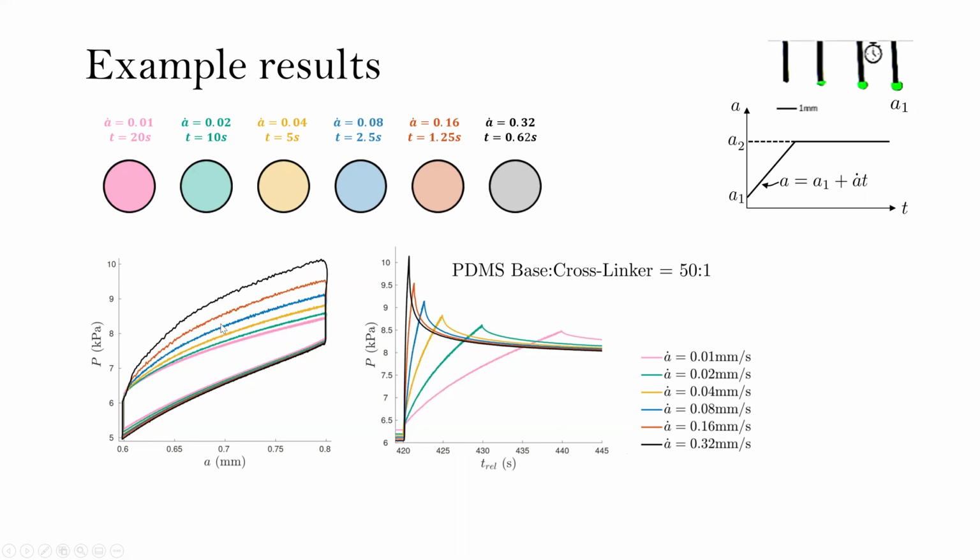We can also see a clear rate dependent effect, where the pressure clearly stiffens based on the stretch rate that we are working with. There's also significant viscoelastic relaxation when you hold the stretch constant. All these are indicators of a significant viscoelastic response. We can even see the pressure relax from its maximum value by almost 40%. So this is not some negligible rate dependent effect.